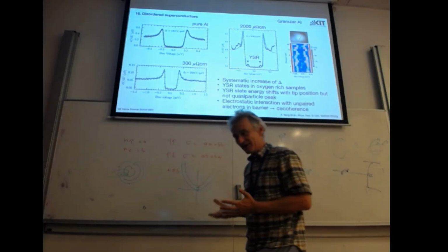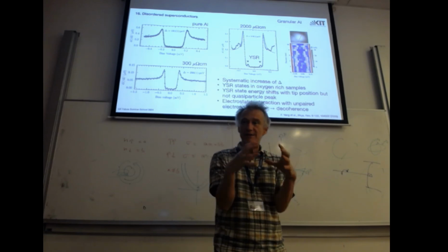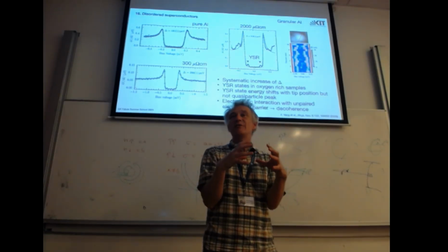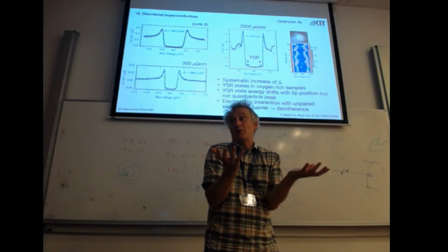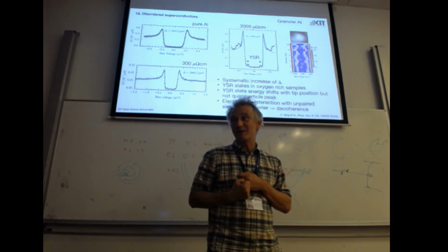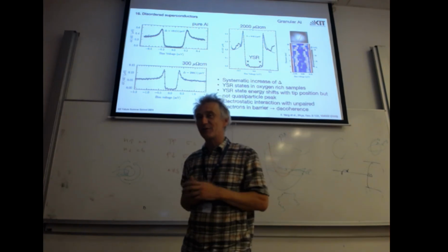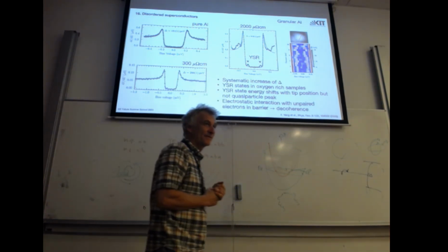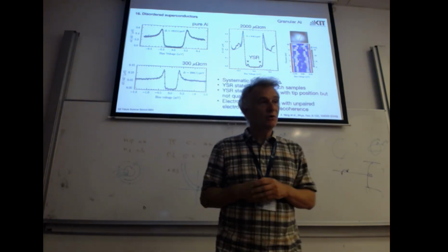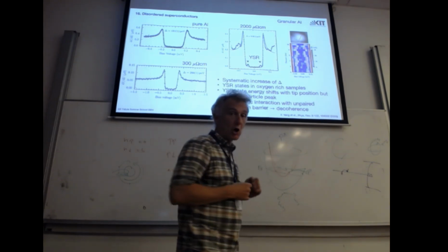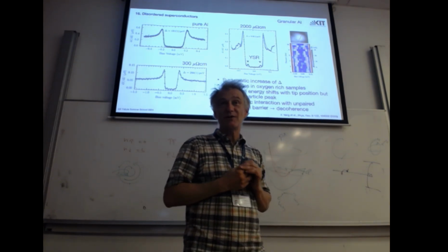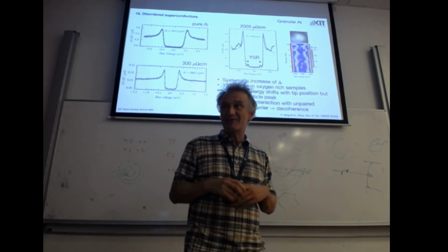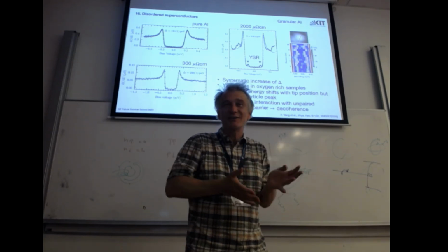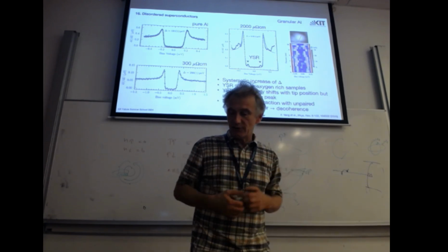And there's a long dispute in the literature about why there should be a Kondo effect. One school says, I have small grains. There can be an even or odd number of electrons. If there's an odd number of electrons, I have a localized magnetic moment, which makes a local Kondo effect on my grain. The other explanation is that my oxide is not stoichiometric. I have dangling bonds, and I have inside the oxide an unpaired electron, which actually doesn't sit on the grain.